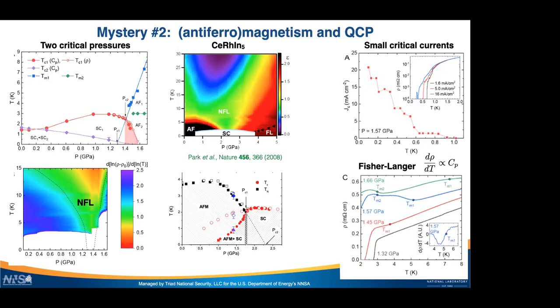And at the transitions, actually, the resistance goes up on cooling, which is also inconsistent with ferromagnetic order. And if we remember the Fisher-Langer relationship, that gives us that the derivative of the resistance with respect to temperature is similar to the heat capacity. The heat capacity is always positive, so one would expect that the resistance would go down on cooling through the transition temperature, but that is not the case here.